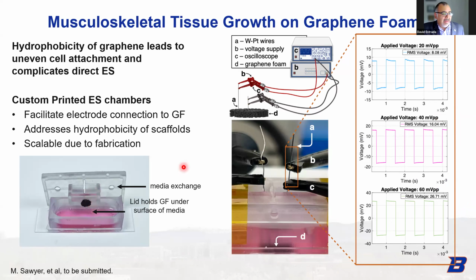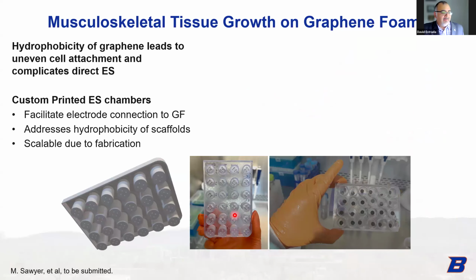And then we added these electrical feed-throughs so we can put electrical contact onto the foam. You can see some of the waveforms we ran through the foam, just showing that we can do different amplitudes and retain the waveform fidelity in this 3D printed structure. It's also scalable, right? It's just using standard SLA printing of a biomed clear resin, and we can scale up to standard tissue culture plates for kind of high throughput analysis.